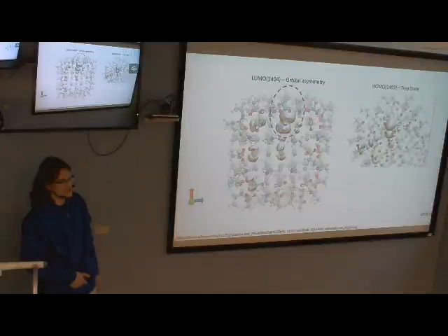And I think my next figure is just another one, without the ligand adsorbed, where there's also some more electron density on the surface. And that was my last slide, but essentially what I've been doing is I took my starter model and just rearranged the ligands in a strategic way so that they shouldn't desorb from the surface as easily. Then I optimized it to where the orbitals look fairly comparable to what they did before, like my initial good model, and then I just restarted these calculations, hoping that would provide consistency between all the models.